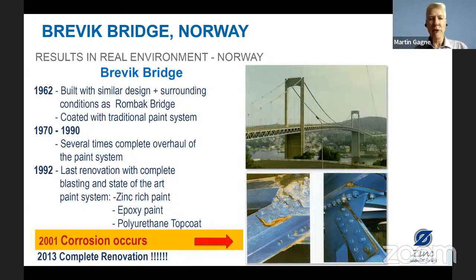They changed the paint system to a more robust one: a zinc-rich primer, an epoxy barrier coat, and a polyurethane top coat. Although still, we can see after 9 years, we had some corrosion evident. And then in 2013, after 21 years, the bridge was fully repainted again.